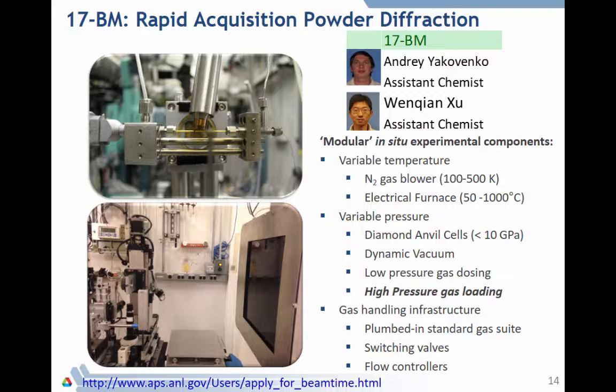How long does it take you to collect data with a 100 micron beam? Actually, not that long, about 30 to 60 seconds. And currently we're using 27 keV. That's the energy at which we are.